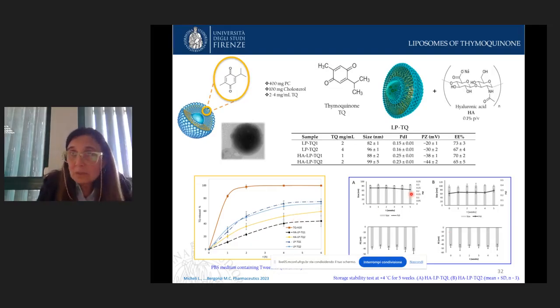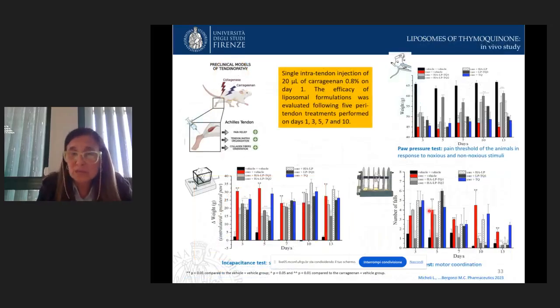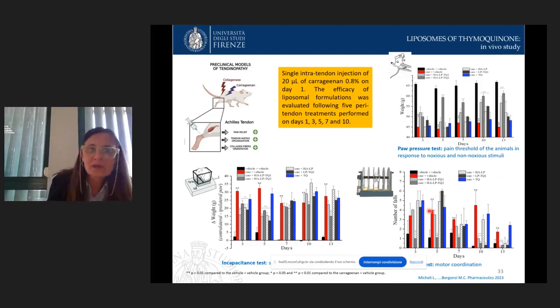The formulations result stable. In this case, we show you the physical properties of the system. Stored at 4 degrees centigrade for 5 weeks, we observed that the size, PDI, and zeta potential remain constant. We tested these formulations in preclinical models of tendinopathy. This is because hyaluronic acid is an excipient, a polymer with anti-inflammatory activity, also used in osteoarthritis or tendinopathy to restore the tendons, to reduce the inflammation, and also to improve the production of collagen. Then we prepared this liposome also to improve the anti-inflammatory activity of thymoquinone.